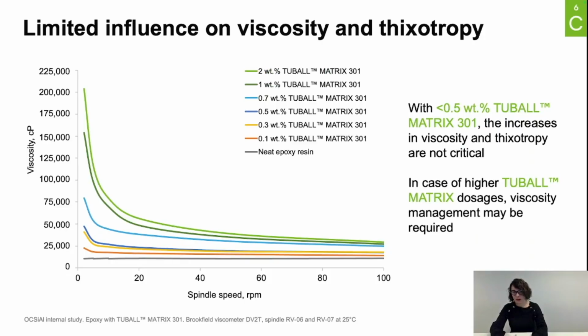Another important parameter for our customers is to manage their viscosity and thixotropy parameters. You remember, the loading level for an ESD flooring is of 0.1% of TUBALL Matrix 301. This is the dark orange line you can see at the bottom of this chart, clearly proving that managing those two parameters will be more than easy for our customers.